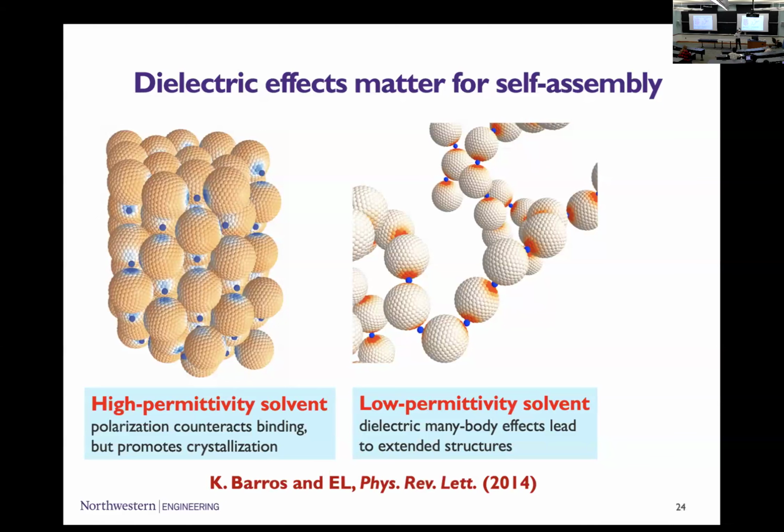Yes, if you bring one negative charge to a particle, you induce a strong attraction. It's that red area that you see on the white spheres. But now remember, it's not charge that you are creating, you're just reorienting dipoles. If you make that point strongly positive, something else has to become negative. So what happens is, the second blue particle arrives, it doesn't want to sit close to the first one, so it goes to the other side.